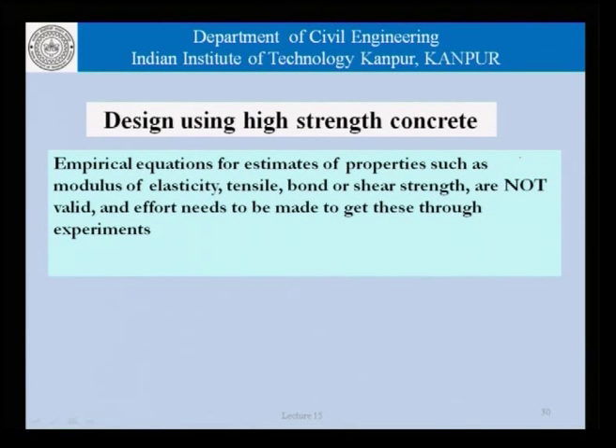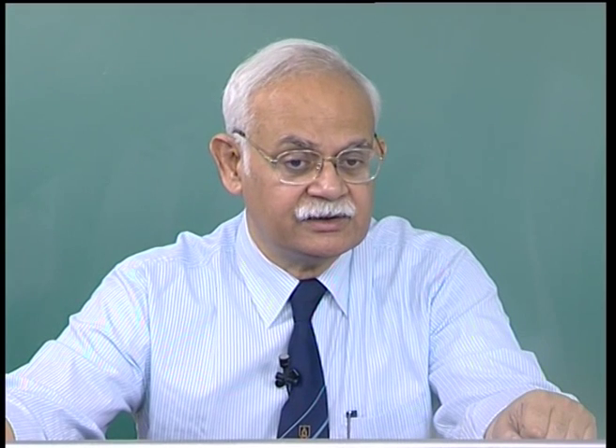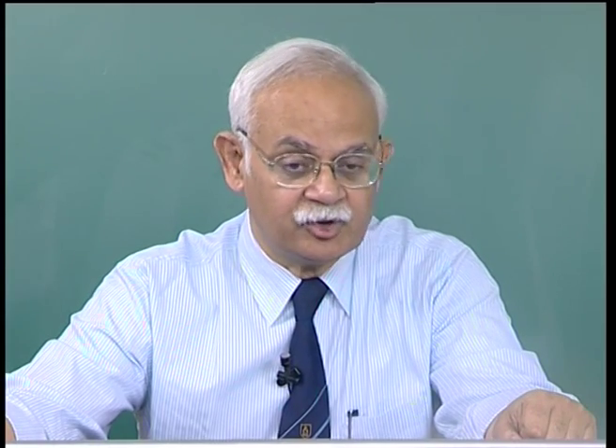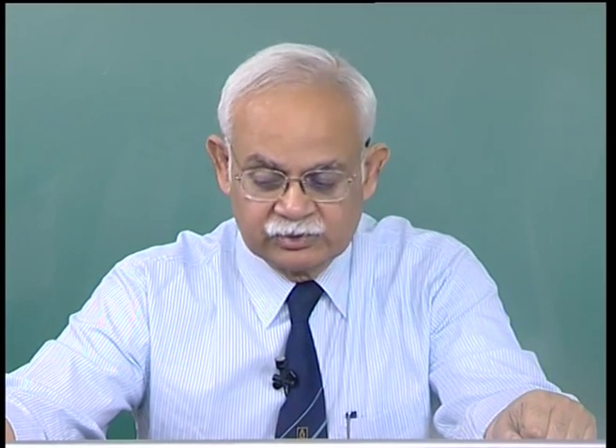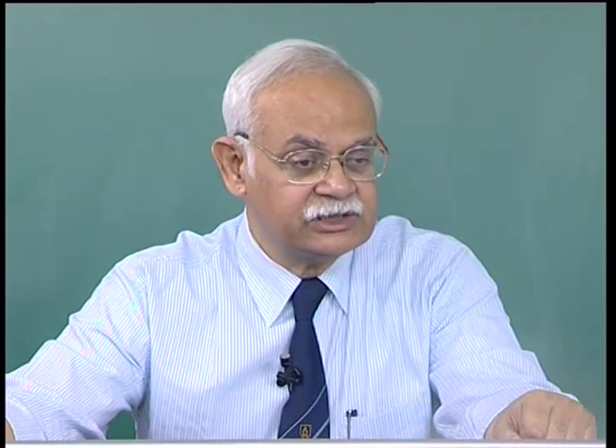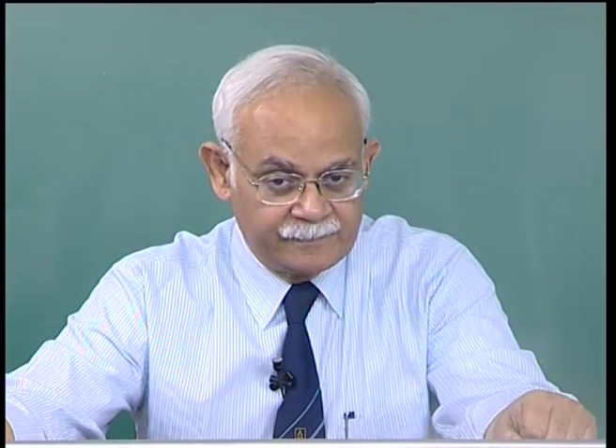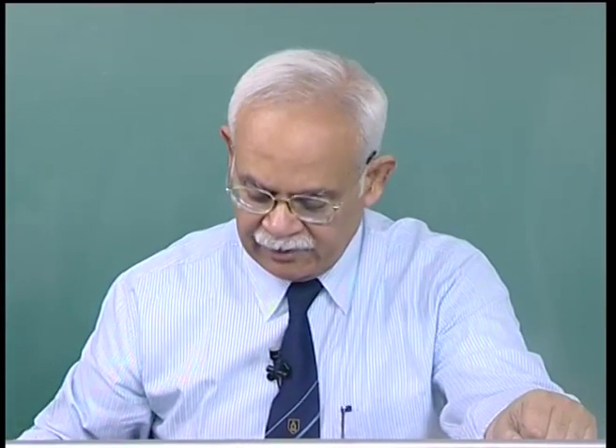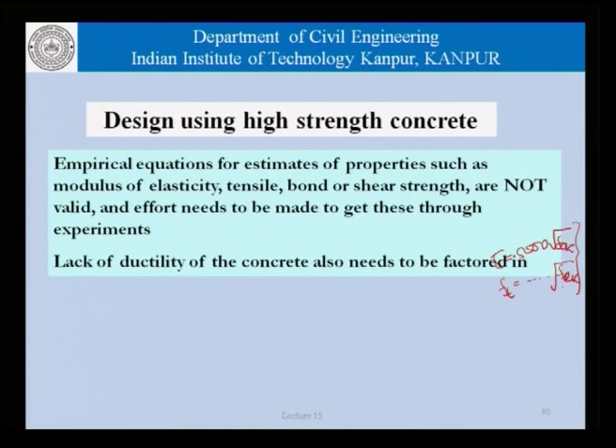Very often a specification will tell us that E can be taken to be 5000 root of FCK, or the modulus of rupture can be taken to be something related to FCK or the root of FCK. These equations are valid only for the range in which they have been tested, and since the data for high strength concretes is not all that voluminous, it is not prudent to use these kind of correlations which exist for normal concretes for high strength concretes as well, and that is something which the designers have to keep in mind. Also, the lack of ductility of the concrete needs to be factored in.